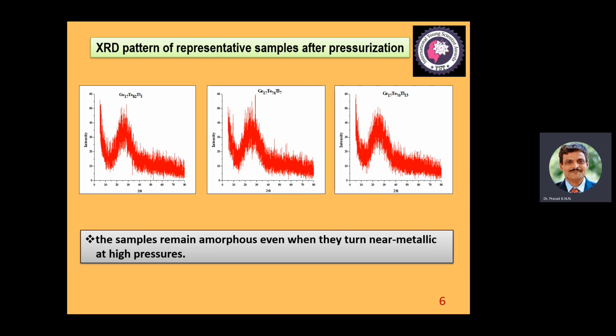So that transition is being noticed, and we wanted to check whether our glass, which is amorphous in nature before pressurization, is being changed to crystalline after pressurization. So to know that, we went for XRD. Again, it is very clear: the samples remain amorphous even when they turn near metallic at high pressures.